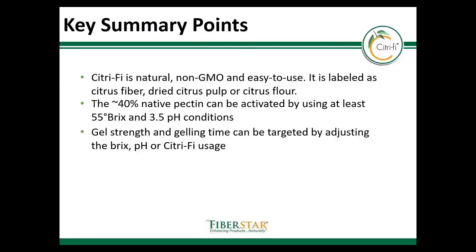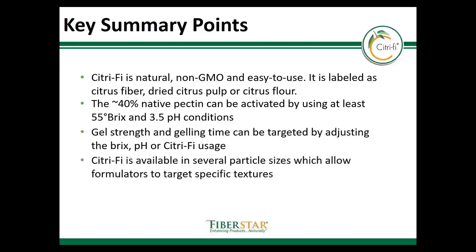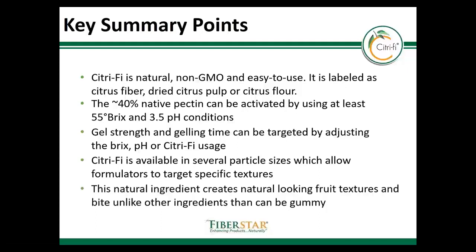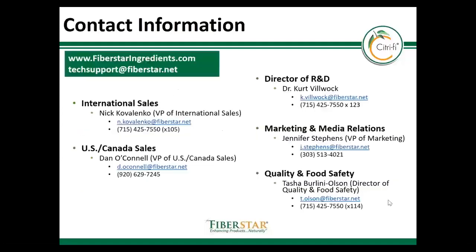The gelling strength and gelling time can be targeted by adjusting the brix, pH, or the Citri-Fi usage rate. Citri-Fi is available in several particle sizes. This allows you to target specific textures. And this natural ingredient creates a natural looking fruit texture and bite, unlike other ingredients that can be gummy.